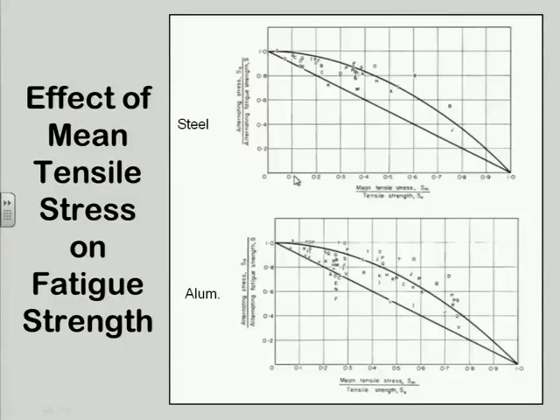But now as we introduce mean stress in addition to that, and it's tensile, we find that our parts fail at values below that so-called endurance limit. And these little letters here all represent test data, and those are the points at which the various pieces failed. And they had to be tested for millions of cycles in order to get that data. The top plot is for steel, the bottom plot's for aluminum, and they look very, very similar.